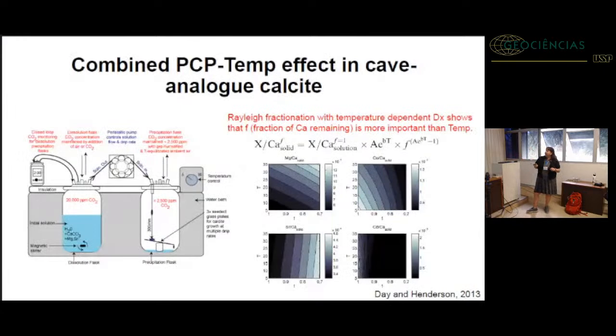Okay, so there are some other complications, like temperature. All of that assumes that the distribution coefficients are constant, but as we have already talked about, they can vary over time. And so the Day and Henderson experiments found this temperature dependence of D magnesium, and they were calculating the effect of prior calcite precipitation, which is in this case modeled as a Rayleigh fractionation type process, where you're progressively removing calcium from solution and enriching the remaining magnesium calcium dependent on the distribution coefficients, and then they incorporated changing temperature in here. This is showing temperature versus F, or the fraction of calcite removed, so basically PCP is proceeding to the right here.